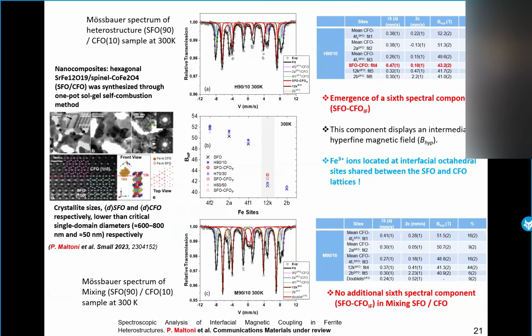For the nanocomposite of strontium hexaferrite and cobalt ferrite, the spectrum at room temperature is not so different from the spectrum for pure strontium hexaferrite. But here, normally we expect 7 sites: 5 subspectra from strontium hexaferrite and 2 from cobalt ferrite. But the hyperfine parameters of the octahedral and tetrahedral sites of cobalt ferrite are not so different from the hyperfine parameters of the octahedral and tetrahedral sites in strontium hexaferrite. For that, I obtained directly the mean information.